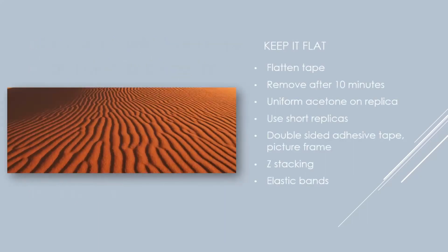And the last slide I'm going to go over is that sometimes the problem is these replicas aren't flat, and that gives you a big issue, because either you're going to have to do a lot of image stacking, or you're not going to be able to do quantitative metallography that easily. So you want to keep these things flat as much as possible. When you get the tape, I just flatten it under some books. When you apply it to the surface, you don't want it to fall off, otherwise it'll just shrivel up like a shrimp chip. You want to apply the acetone uniformly, use short replicas, and you can use Z stacking software. It's just time consuming. And that's probably about it.